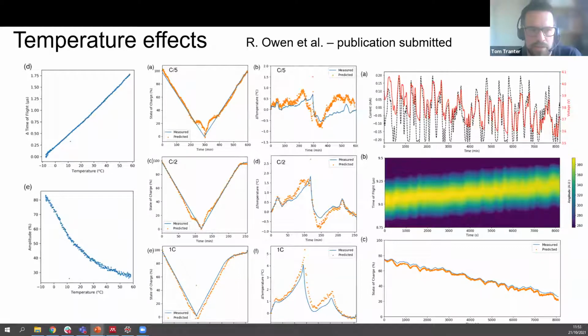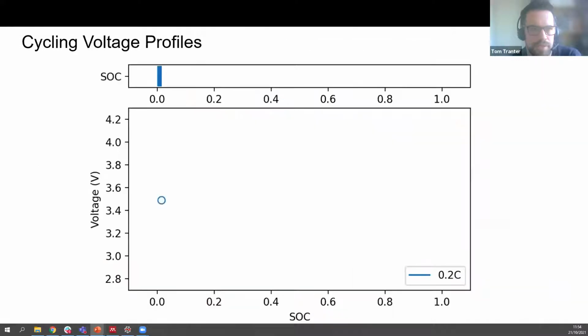And just applying standard lab-based regression, varying temperature and varying state of charge, we can get reasonable predictions for what the state of charge is purely from the change in time of flight of certain key peaks in the signal. However, doing machine learning enables us to improve on those predictions.